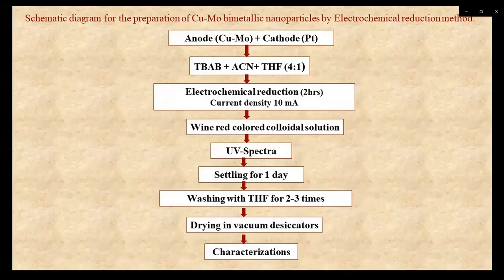Here we use copper and molybdenum metal sheet as sacrificial anode and an ingot platinum metal sheet as cathode. The electrodes are placed 1 centimeter apart from each other. Acetonitrile and tetrahydrofuran in 4:1 ratio is used as electrolyte. 0.01 molar tetrabutylammonium bromide is used as stabilizer. The reaction is carried out for 2 hours at 10 milliampere current density. After 2 hours, we get wine red colored copper molybdenum colloidal particles. These colloidal particles are left settling for 1 day. After settling, we wash it with tetrahydrofuran 2 to 3 times and dry it in a vacuum desiccator. The dried samples are used for the various characterizations.